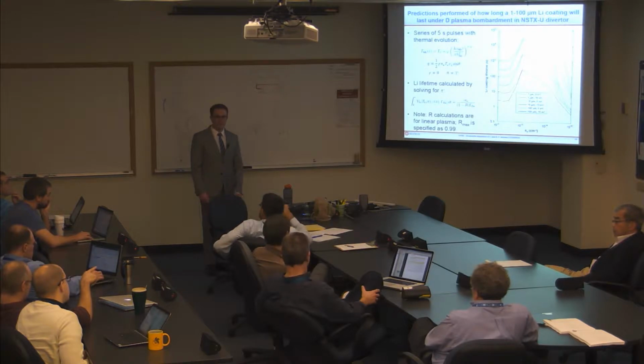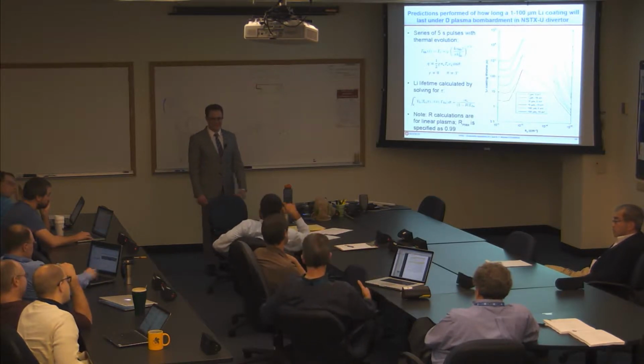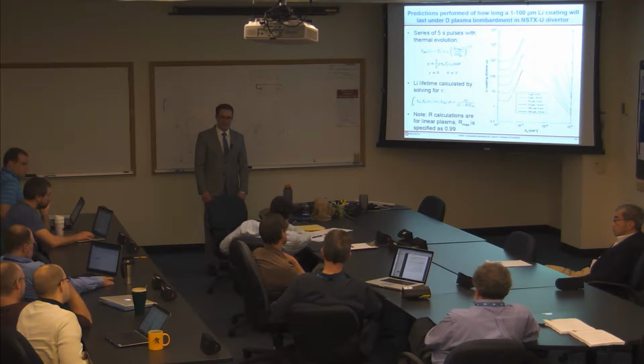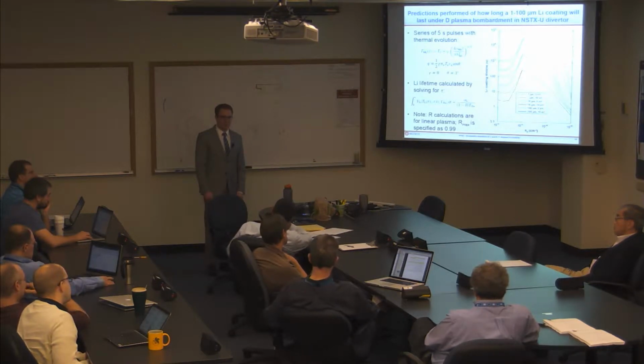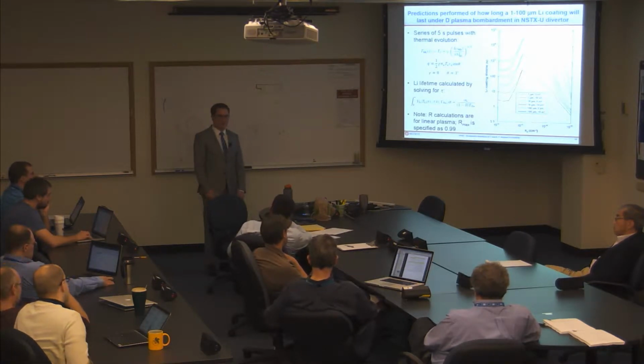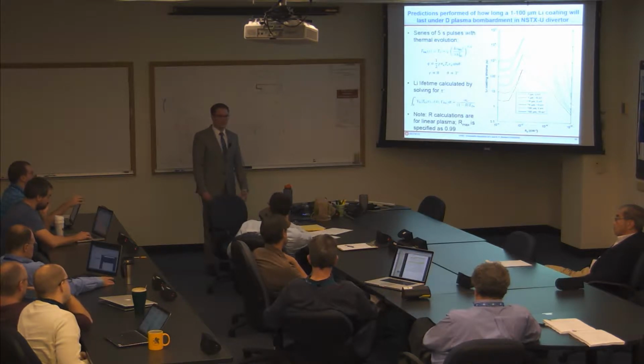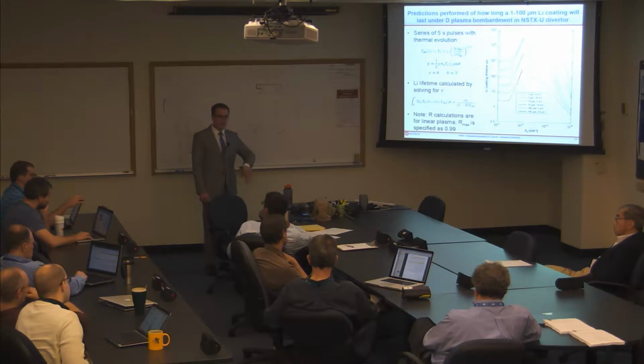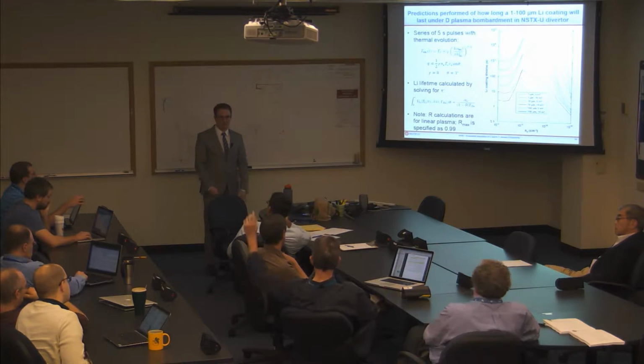Yes, you should. Well, you did do experiments on graphite substrate. Yes, we did do experiments on graphite substrate, which I didn't include mostly just because of time constraints. You see that the lithium emission rate very quickly decreases, which is indicative of the lithium intercalating into the graphite matrix. So you don't actually maintain the pure lithium coating on top of the graphite to be eroded into the plasma. Thank you.